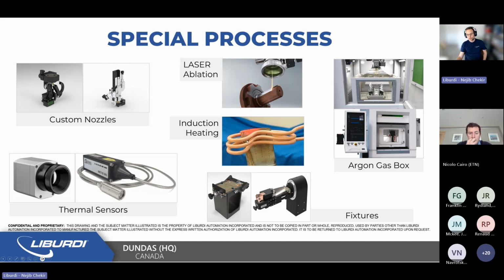And in this case, it generally includes induction heating in order to virtually make unweldable materials weldable and prevent them from cracking upon cooling down from the melt pool to the solid phase. And in this case, that would, as I said, include a typical induction heating coil that would preheat the blades, the area of interest, at a specified temperature, and minimize that delta T in temperature between the liquidus of the melt pool and the solidified end temperature upon cooling down. And these again can be automated, so can be integrated in the platforms that I've shown earlier and be automated into repairs.